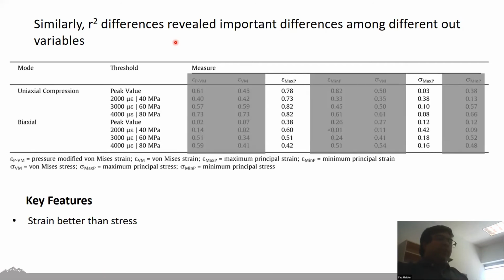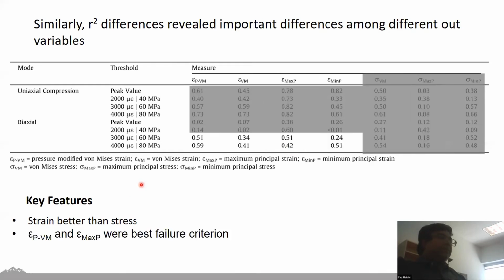So here are some of the things that we identified when we looked at our tabular data. One of the things we noted was that, as we hypothesized earlier, strain-based measures generally did better than their equivalent stress-based measures. And I think that becomes most obvious when you look at maximum principal strain versus maximum principal stress. Clearly, the R-squared values for the strain measure are just much, much higher in this case.